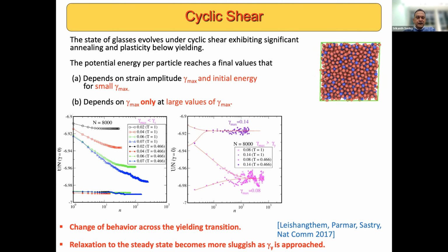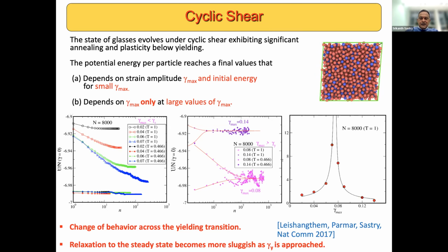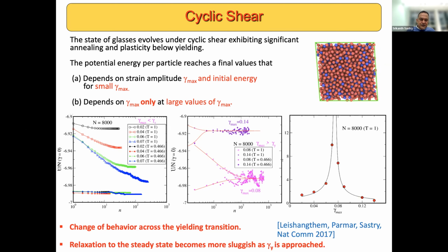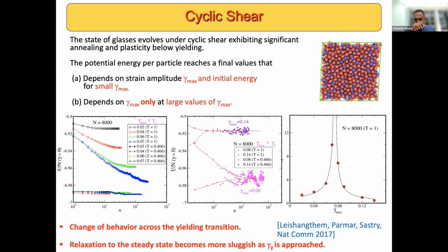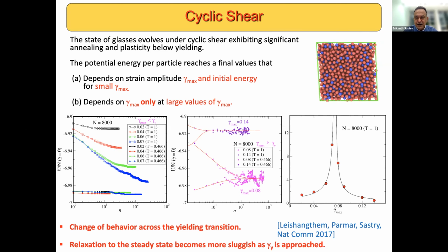And in between these two regimes is the yielding transition. And one interesting thing which you can read off from these graphs, which is going to be relevant for the later part of my talk, is that the time it takes to reach these steady states is a non-monotonic function of the strain amplitude, which appears to diverge at the yielding point.